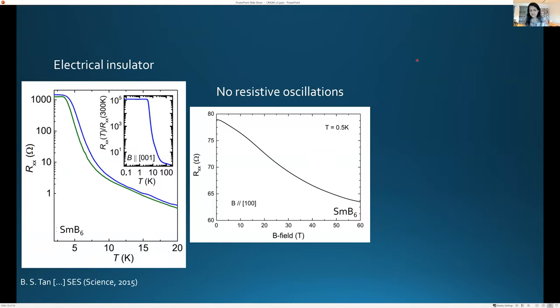If you think a bit about it, it will make sense that if we're expecting only a fraction of the sample, the surface of the sample, to be conducting, we would not expect a property sensitive to the entire volume of the sample to show oscillations. Rather, you would expect something that sees the conducting parts, like the resistivity, to show oscillations. So we try measuring SdH, Shubnikov-de Haas oscillations.